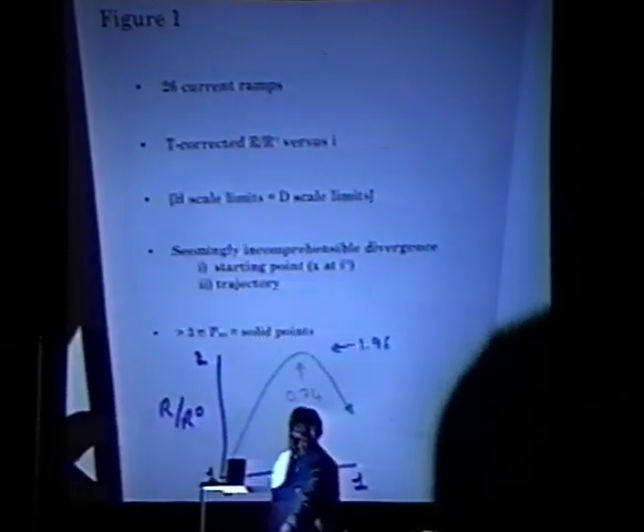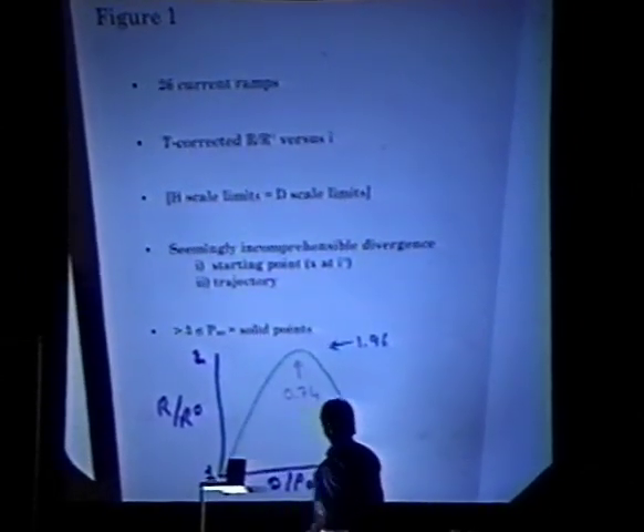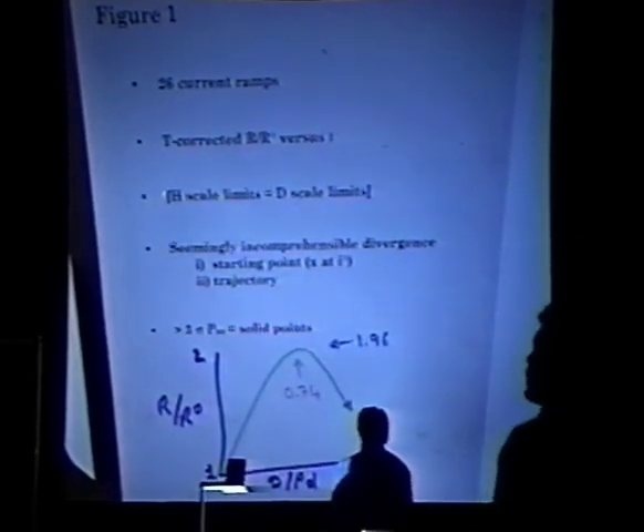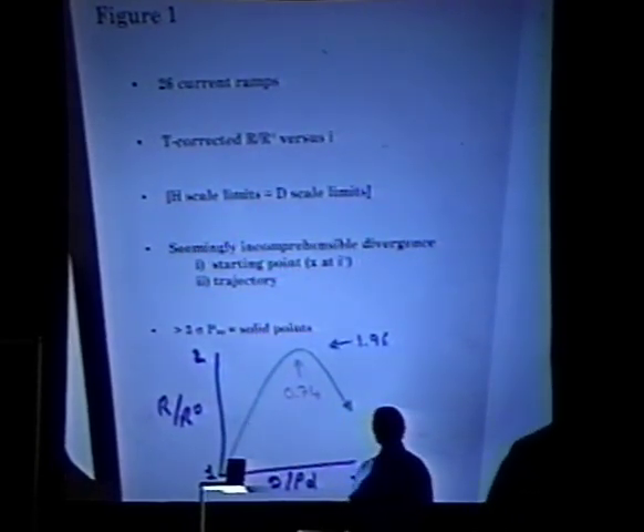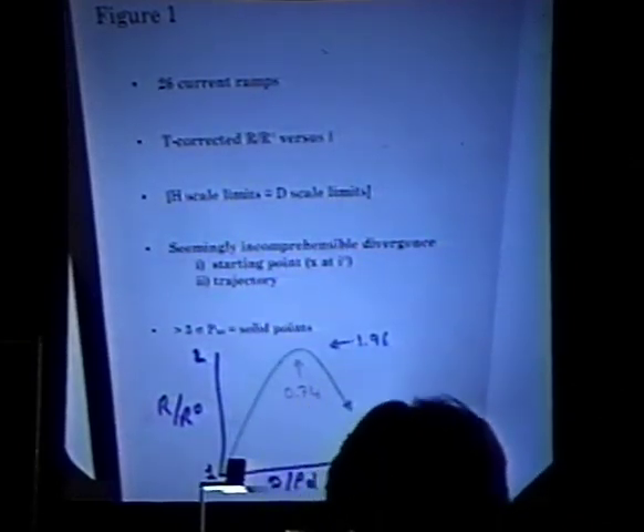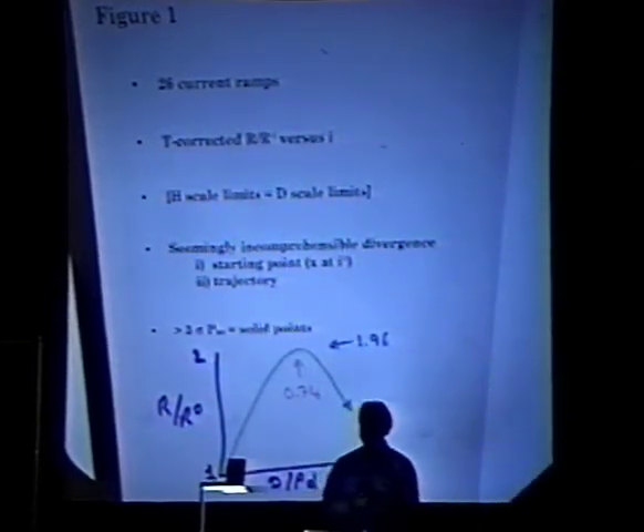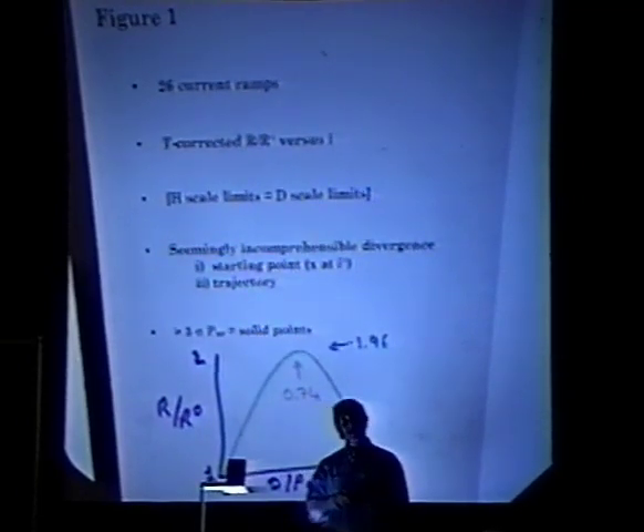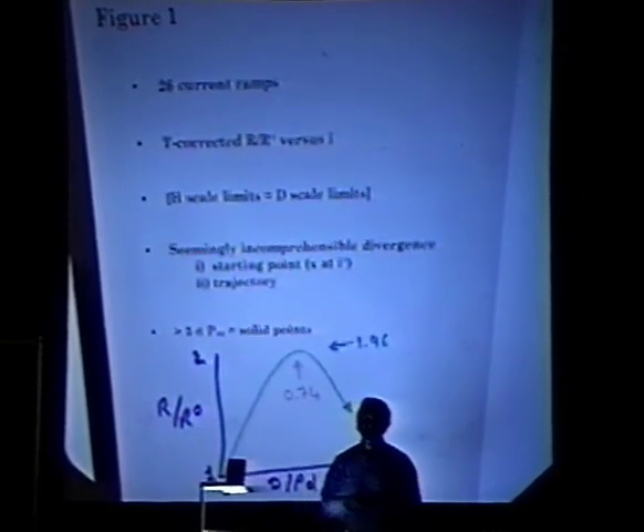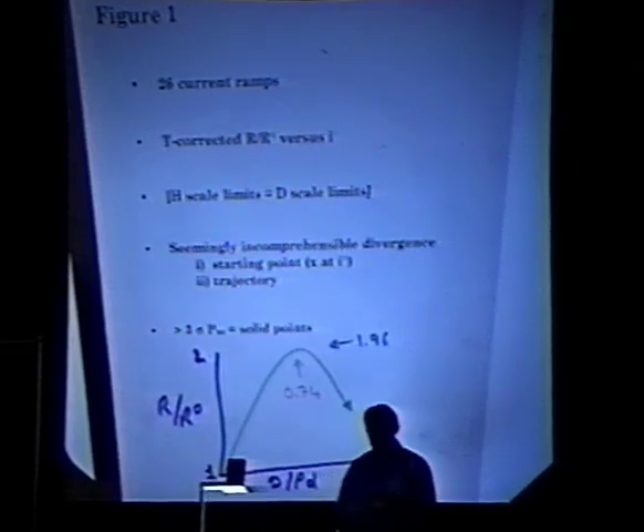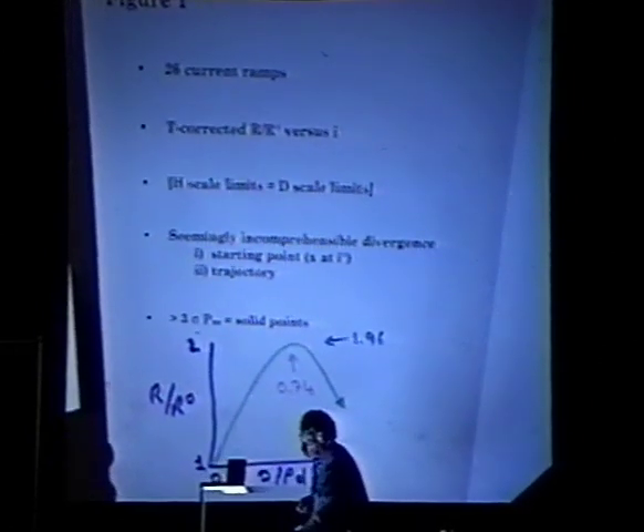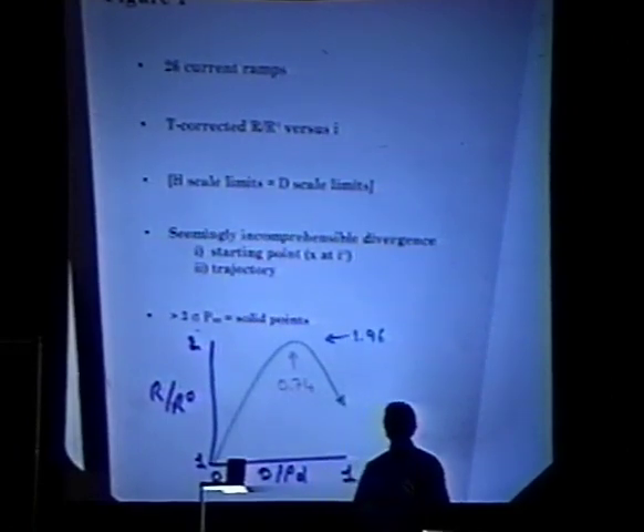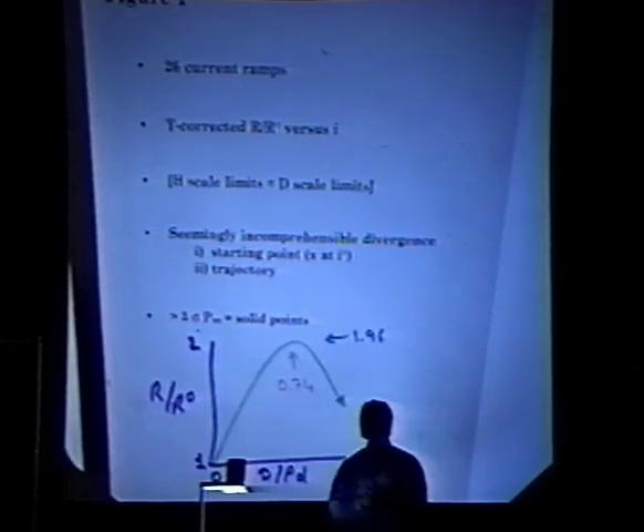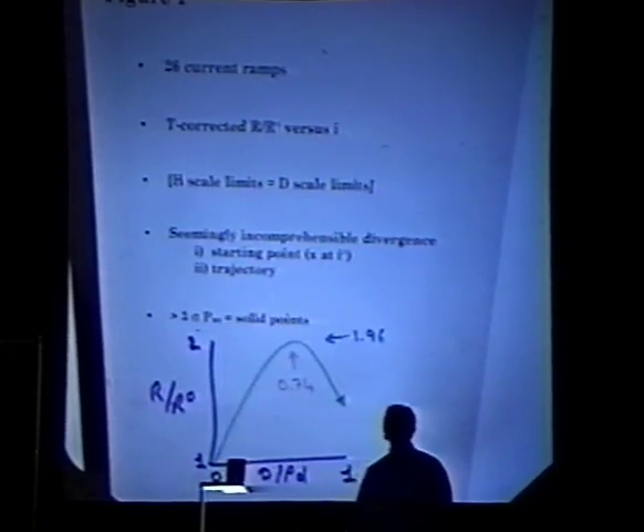Now, having said that, I've selected 26 identical experiments, one hydrogen experiment, the rest of them deuterium experiments. The result is seemingly incomprehensible. The 26 experiments yield 26 unique and entirely different results, despite the fact that we've taken extreme precautions to maintain the electrolyte and the electrode and electrode surface condition the same in all experiments. The current ramps are at the same rate.